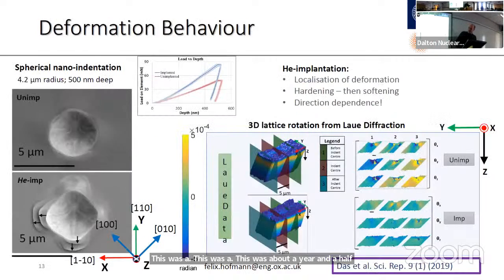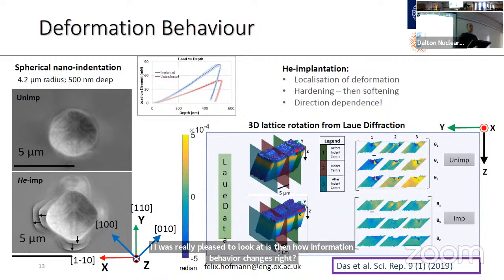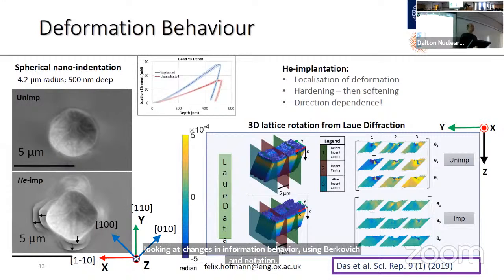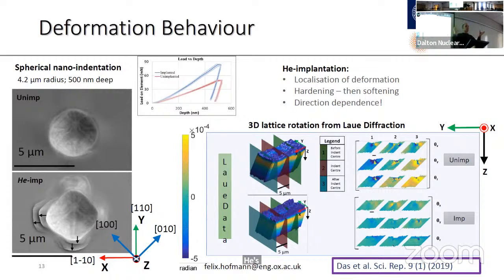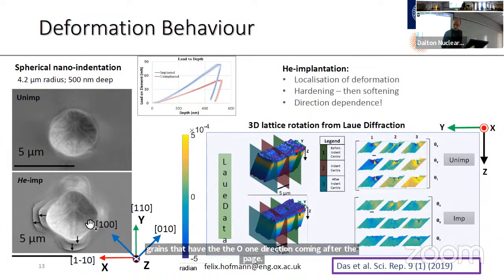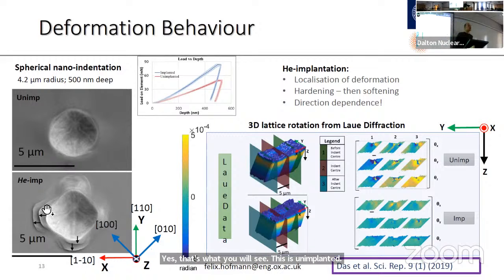So that's quite good. Anyway, the other thing that I was really keen to look at is how deformation behavior changes, right? Now, looking at changes in deformation behavior using Berkovich indentation is a pain because everything is dominated by the shape of your indenter. So rather than looking at Berkovich, we said, well, okay, why don't we go down to spherical indentation? So this is unimplanted material. I'm looking at grains that have the 001 direction coming out of the page, so towards you. This is unimplanted, this is helium implanted, and you straight away notice that there's this dramatic change in the structure of the pileup, with these slip steps here and much more localized pileup. You also see that the load during the indentation is much higher.